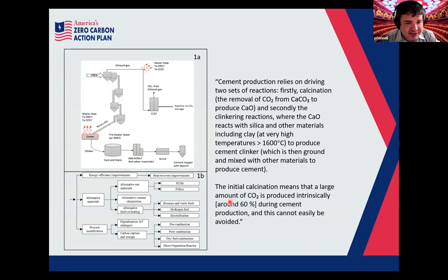Here is just a brief slide showing, in a stylized manner, the cement production process. You feed in your limestone up here. It goes down through a set of cyclones and into a kiln. It's not quite this extreme angle, I think the limestone would just fall straight out if it was at that angle. In the kiln, reactions happen: the limestone is reacted with sand and clay and a few other bits and pieces to make a mixture of calcium silicates. Those are what are actually the glue in cement that binds it together.